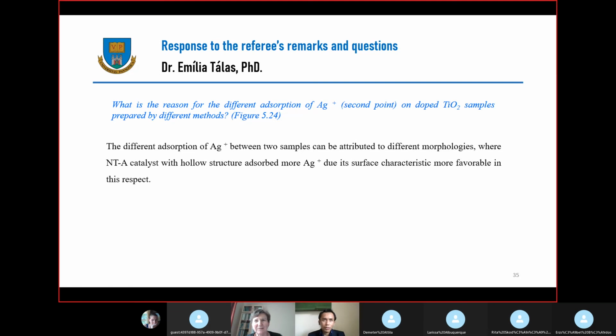Yeah, we can imagine the first adsorption, because we stir it before the irradiation to homogenize this mixture. In the adsorption, the silver is still in ion form, but after starting the UV illumination, this adsorbed ion is reduced to silver 0, and there is also another adsorption maybe during this UV illumination. I mean, the following adsorption occurs and then reduction also, because the concentration of the silver is very small. Yeah. Okay. Thank you.